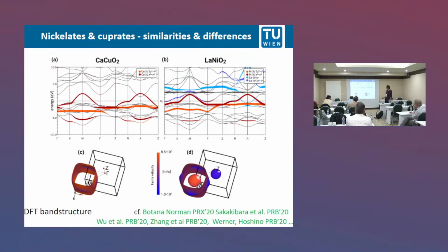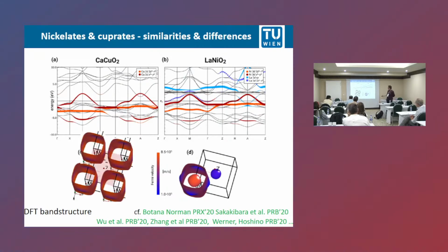That is the DFT band structure of calcium copper O2 and lanthanum nickel O2. And they are quite similar, but also different in some aspects. So you see here the x²−y² orbital crossing the Fermi level. It gives rise to these hole-like Fermi surfaces. Or if you go to the red dashed first Brillouin zone, then you have 4 of these Fermi pocket sheets in the cuprates, as you know.